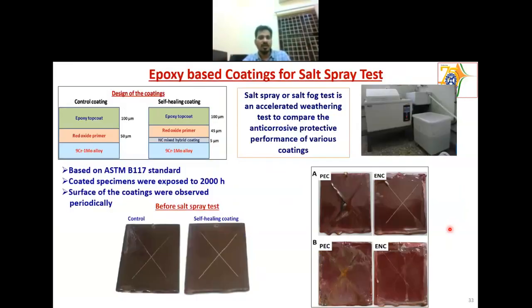So this is the container we used, and then using that container we made a coating. This is the design of the coating, and this coating we applied on 9Cr-1Mo ferritic steel. Both the coatings have the same thickness, 150 micron. The difference is that in this coating, we have a nano container mixed hybrid coating. This is a sol gel based coating only, TiO2 and silane coating here we gave. And in this layer, we added this nano container.